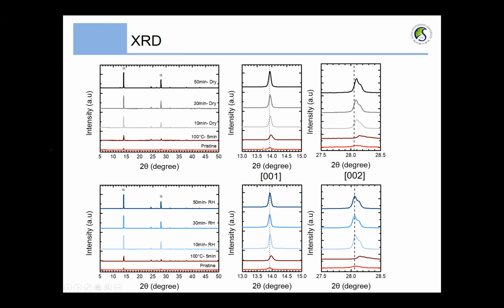This is because the MACl is incorporated into the FAPbI3 lattice, inducing volume shrinkage. But with prolonged annealing time, the peak shifts to a lower angle, which reflects that the MACl is evaporated or eliminated. You can also see that the humidity condition shows a much lower peak position than the dry condition, which implies that the MACl is preferentially eliminated or evaporated during the annealing process.